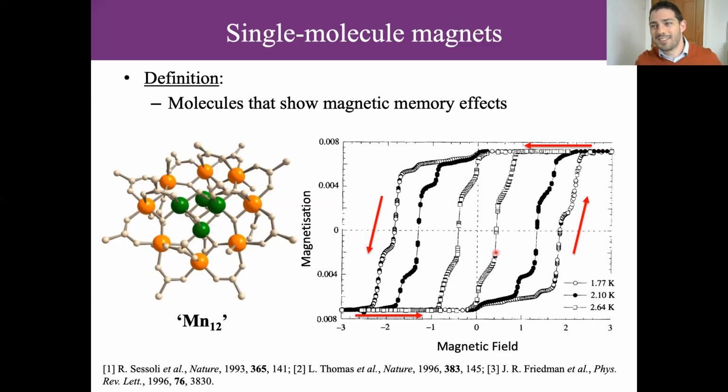All right, so how does this work loosely? We'll go through the details of this during this lecture, but the main background is we have some memory effect. And so the key experiment we have in magnetometry is a hysteresis experiment. This is where we change the external magnetic field and measure the magnetic polarization, or the net magnetization, of a sample. So in positive magnetic fields, we can positively magnetize the sample, and as we reduce the field back towards zero, the magnetization is retained, and it requires a negative magnetic field, so a field in the opposite direction, in order to magnetize it in a negative direction.